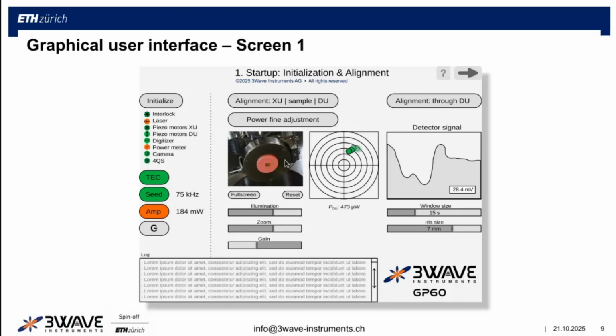This is particularly useful if you have multiple samples installed and you want to choose a particular one, or if you have a small sample, to make sure you really hit it. Then you can also control the power in a finer way, and you have a screen that gives you a target on the detection unit. You see that the laser beam hits the sample by the camera, and then it goes to the detector, and on the detector you have this screen, and you can manipulate the detector X, Y in order to make sure the beam hits the center here.